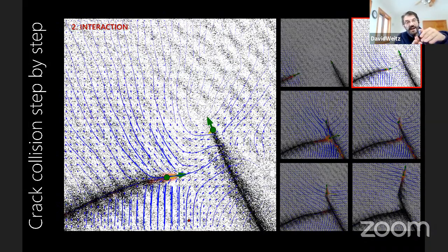And that causes the fact that you have this long-range strain, that causes this crack to form, to change its direction and go in the path where you can get the most strain to pull it apart. And that becomes essentially normal to the first incoming crack. And you can see the large strains that are driving that.